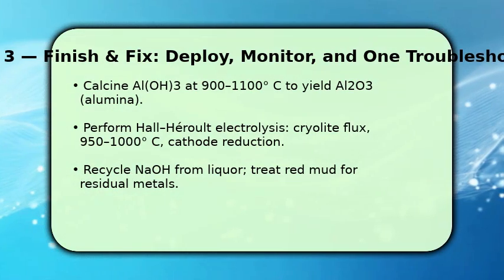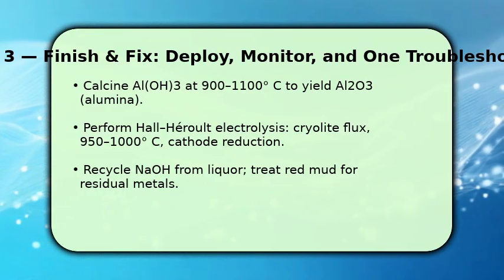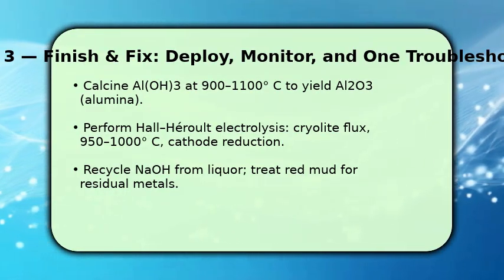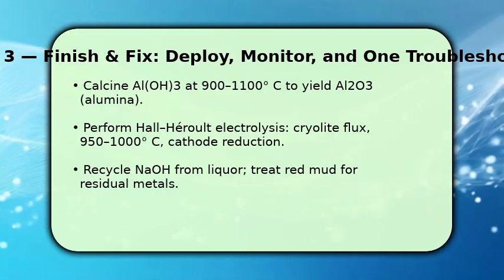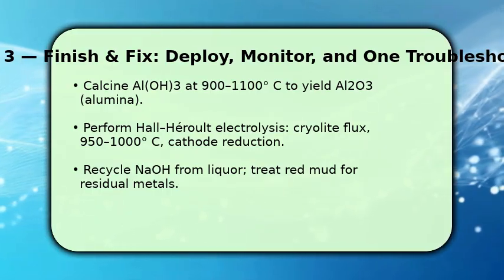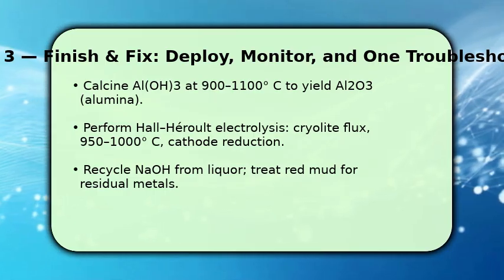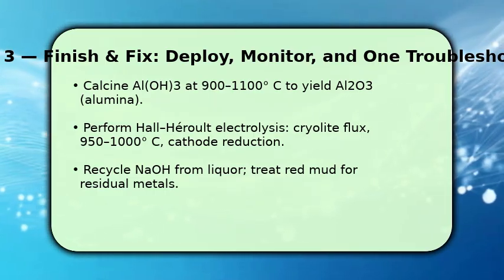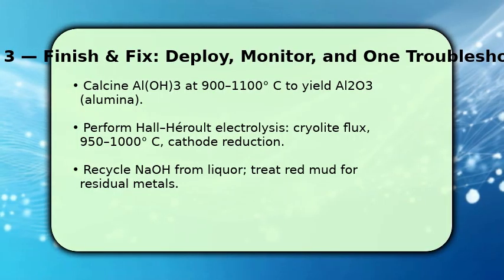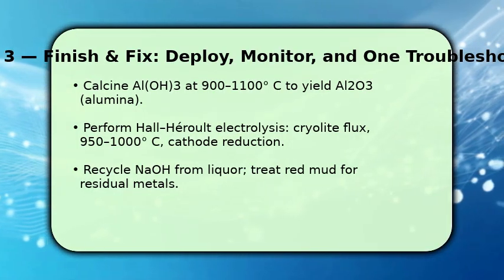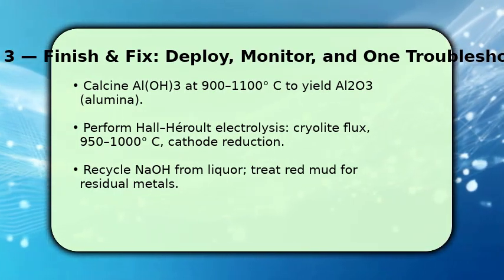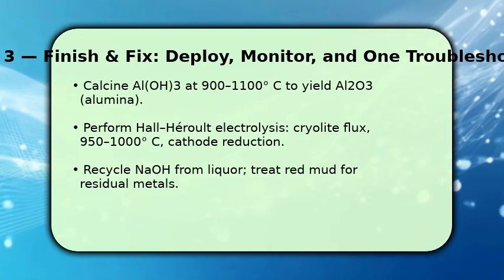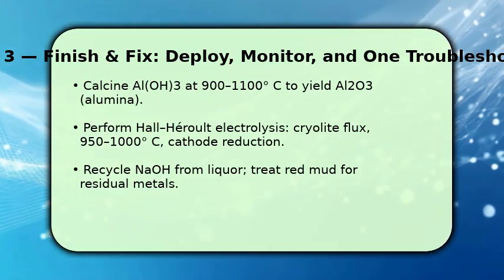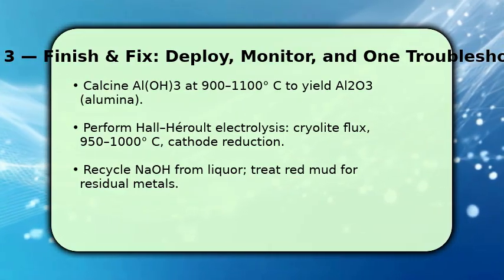You now convert precipitate to metal. Dry and calcine aluminum hydroxide at about 900-1100 degrees C to produce alumina. This removes water and readies the oxide for electrolysis. In the Hall-Héroult cell, dissolve Al2O3 in molten cryolite, maintain 950-1,000 degrees C, and run large current so aluminum ions reduce at the cathode. Collect molten aluminum.